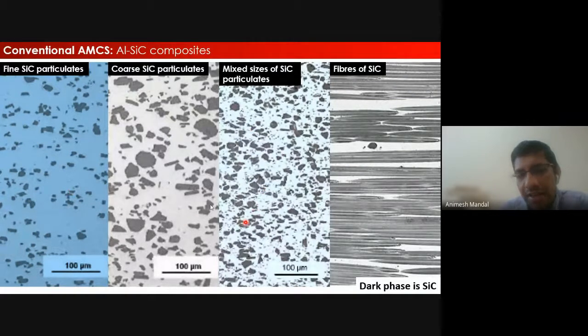So as a result, you can generate different kinds of properties in all of these composites. In the same silicon carbide, just by changing the size, and not only that, by changing the volume fraction, you can play with the properties.